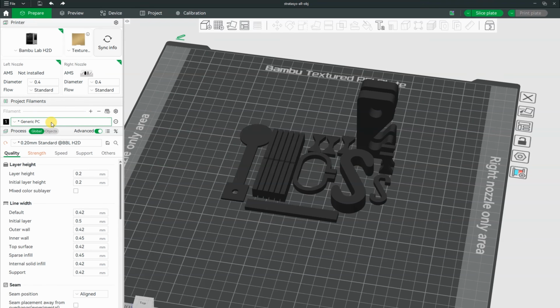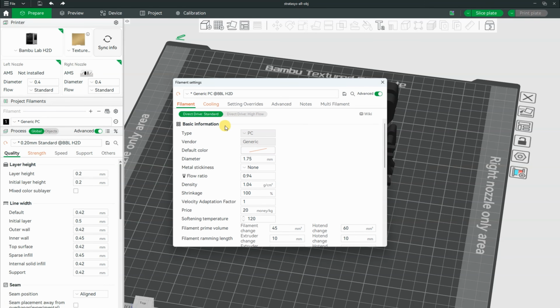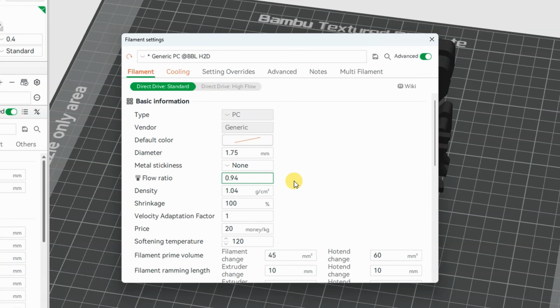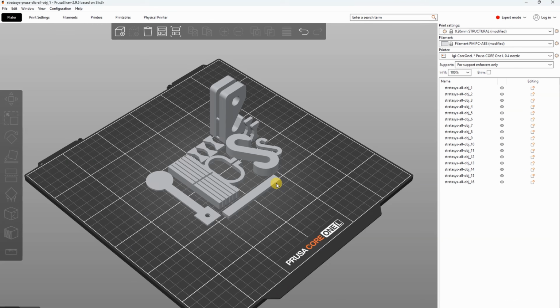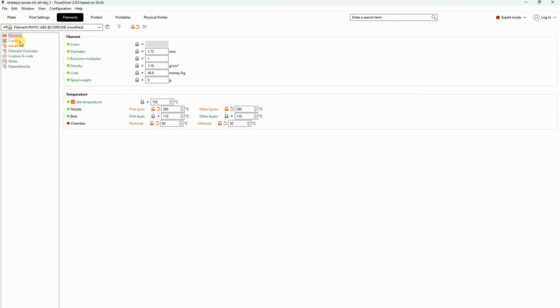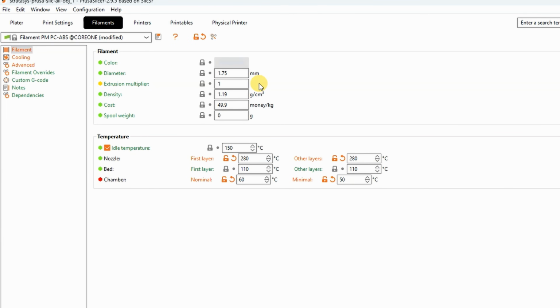In Bambu Studio, for generic PC, the default setting for the flow ratio is set to 0.94. In Prusa Slicer, the default setting for the material I used is extrusion multiplier, and it is set to 1, correctly. I don't really understand why anybody would set such a low default value for the flow ratio. I mean, it's calculated from the geometry.